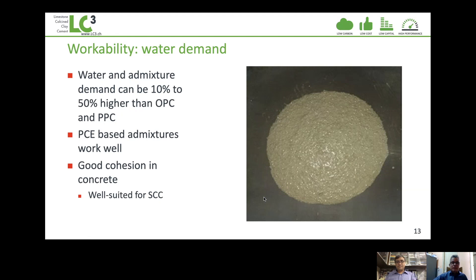Professor Martirena now takes the floor. Now we're going to talk about practical applications of concrete and products containing calcined clays and limestone, like the LC3 system. We have to remember that calcined clays have a very high specific surface, meaning they have a high water demand, and we likely need to increase the dosage of plasticizers. In our experience, PCE-based superplasticizers work pretty well, and we see very good cohesion in concrete with very little bleeding — including in self-compacting concrete applications.